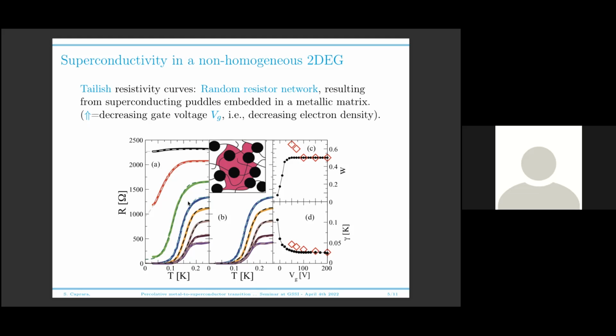You start from a metal to a superconductor, and when your superconducting fraction for some reason goes below the percolation threshold, which for homogeneous disorder in two dimensions is 1/2, then you don't reach a superconducting state at zero temperature. You end up in a metallic state with a much lower resistance because you have a lot of superconducting islands embedded in the metallic matrix, but nonetheless, in the end, you do not have a superconducting percolating path from one end of your system to the other, and then the final total resistance is finite.